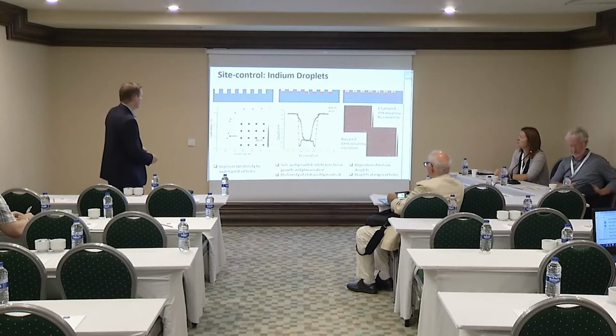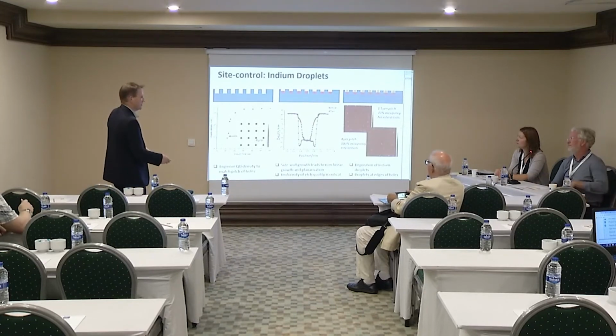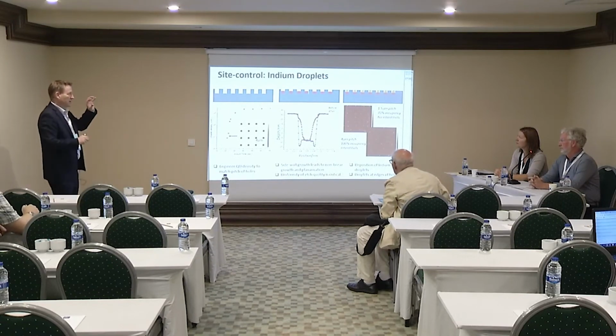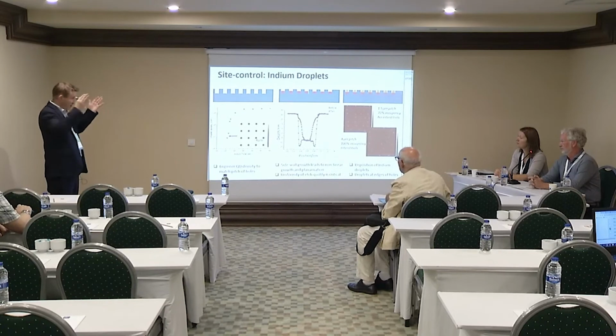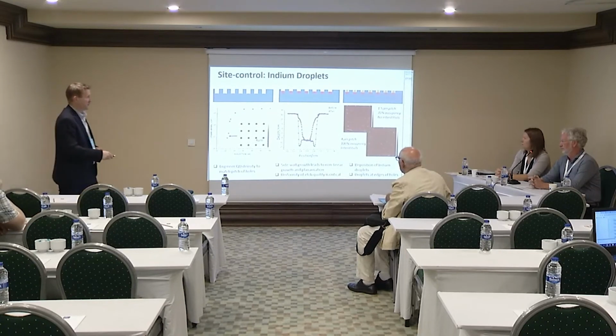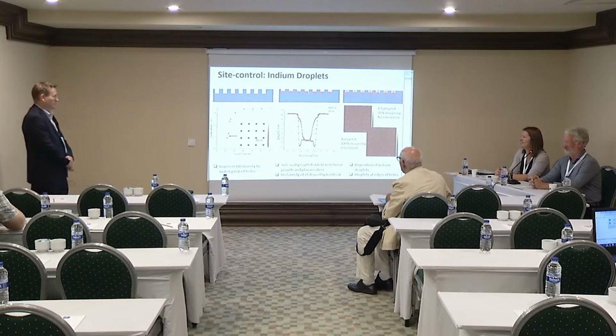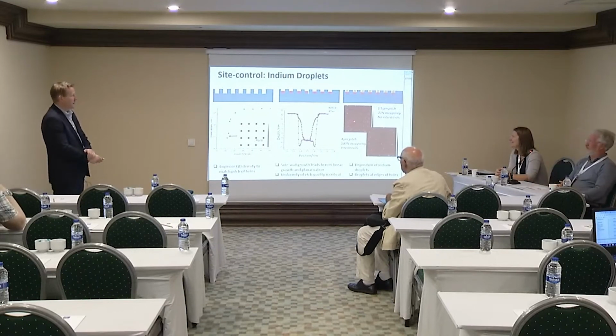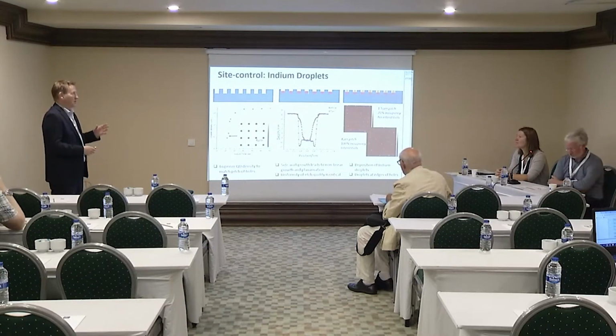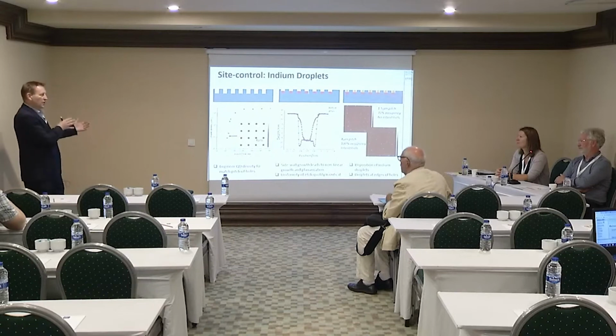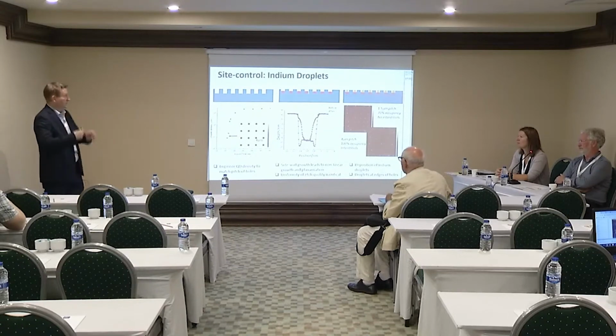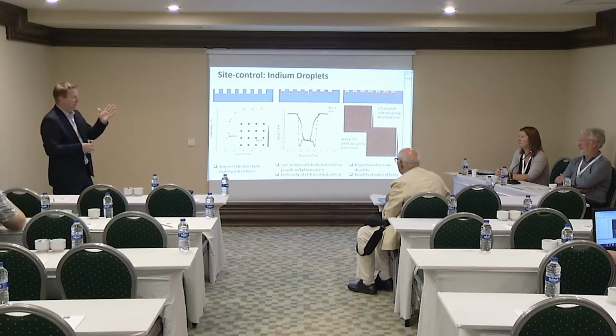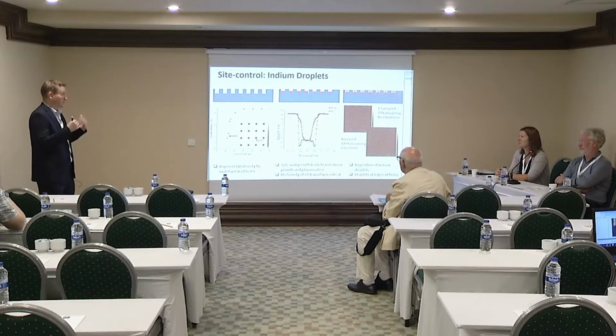I should say that this is really just a snapshot of a broader study that we've done, looking at the size of the holes, the pitch of the holes, the depth of the holes, etc. And these are the best results from that. Part of what we really want to do is bring the hole size down to have it more matched to the droplet. But we've partly worked on larger holes because we need to control the etching. You want to make sure that you know what you've got in the etching and in the buffer layer growth before you start thinking about what's happening with the dots. So the next step is to move down to smaller holes and properly study the interaction.